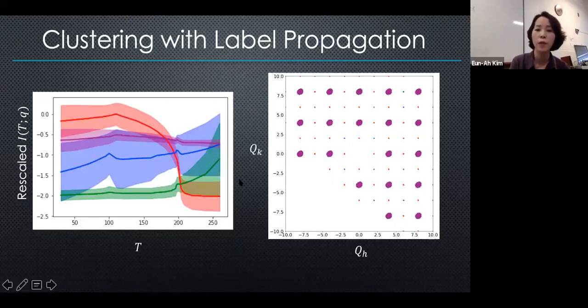When the spread is tight, you know this mean is meaningful. And when this mean behaves in this way, such as looking like an order parameter, you know you've discovered an order parameter. Your algorithm does not know about order parameters, but because it's sorting the data for you into different temperature dependencies, you can immediately discover that you have an order parameter. Now you can look at where these points came from, because each of these trajectories came from different points in Q space. And what you find is that indeed the red points are coming from the Bragg peaks that are expected of the transition that makes the two tetrahedra inequivalent.